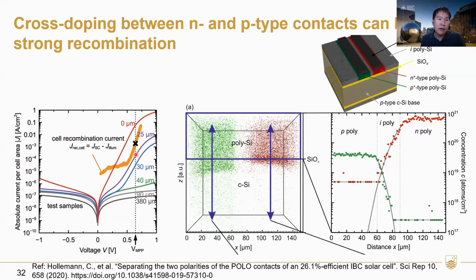So these graphs here are from the group at ISFH who made the POLO IBC, the 26.1% IBC. Here, it plots the gap between the N-type poly and the P-type poly, the recombination current versus the voltage. If we compare at the same voltage at the maximum power point, we see that when the gap is too small, the recombination current becomes very, very large. You do need a sufficient gap to avoid this recombination effect that will be very, very bad for the cell efficiency.